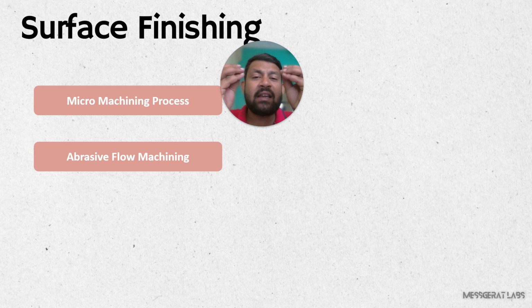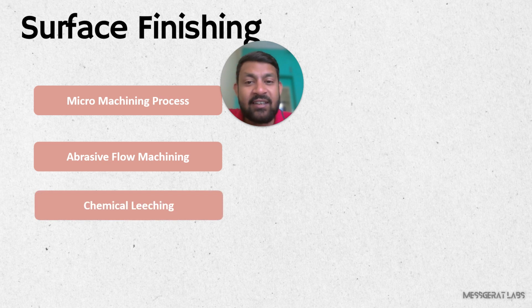So there are abrasive media, diamond particles, which are mixed in a paste. This is something more viscous than the toothpaste that we use. So abrasive flow machining is only used for your internal areas. That is the catch here. Chemical leaching is another chemical-based method which helps in removing the surface roughness of a component by passing the chemical through internal channels. These are mostly used for conformal cooling channels or channels in electric motor casings or other casings provided for the purpose of cooling. Those channels can be cleaned using chemical leaching.